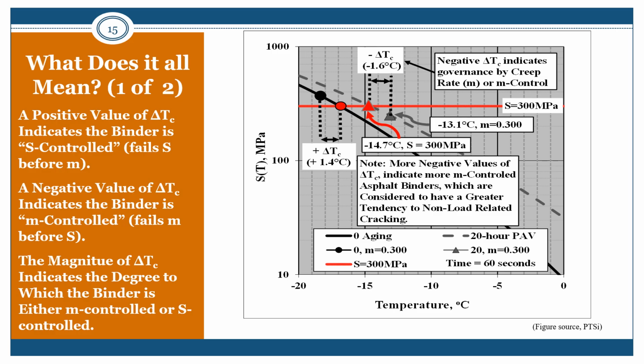What does all of this mean? Depending on the values of T sub CS and T sub CM, the sign of delta TC is either positive or negative, which indicates whether the binder's low temperature performance grade, PG, is governed by its creep stiffness, S value, which is a positive delta TC, or governed by its creep rate, M value, which is a negative delta TC. A positive delta TC value indicates that the binder is S controlled, failing the S criteria before the M criteria, while a negative delta TC value indicates the binder is M controlled, failing the M criteria before the S criteria.